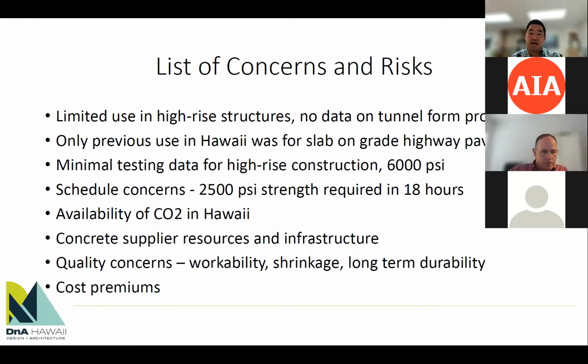But because it's a high-rise project and we had a very tight, aggressive schedule with the tunnel form construction, we actually had a 6,000 psi mix that needed to hit 2,500 psi strength in 18 hours. That strength was required so we could dismantle the forms and move them up to the next floor to keep the cycle going. The one floor a week type of cycle you see on high-rise construction, particularly in Hawaii. So we had concerns there.